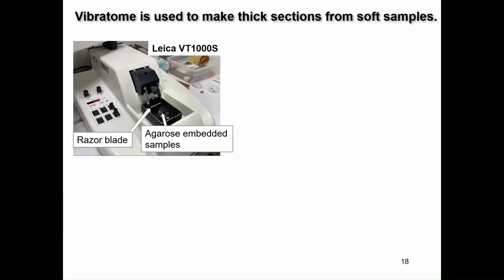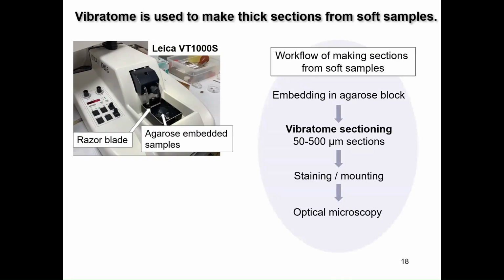We have Leica VT1000S vibratome. Vibratome uses a razor blade that vibrates at high frequency, and then it cuts samples embedded in agarose. So here are the samples, and then there's a sample chamber we fill with water, and as the razor blade advances close to the samples, we can cut the cross section. And the samples have to be soft enough, like the same firmness as agarose gels. By vibratome sectioning, we can make 50 to 500 micron thick sections.